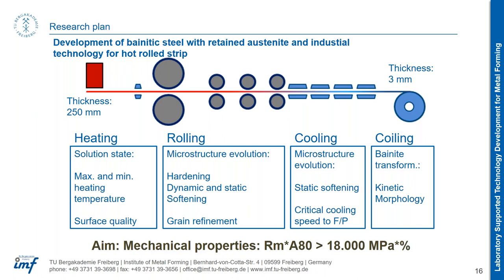By cylindrical tests we can achieve water quenching — we separate the tools, move them out from the sample, and throw the sample directly into water, achieving something like 1000 K/s. How are you measuring the transformation? We use a laser dilatometer. Before 2011 we used a laser dilatometer on the Gleeble — it has an additional channel for the laser dilatometer so I can measure the change in dimension of the sample with a red laser.